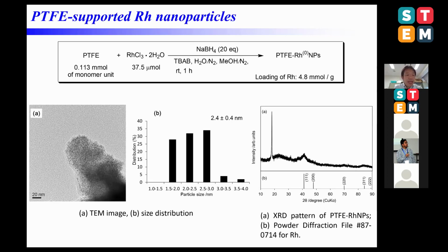PTFE-stabilized rhodium nanoparticles were also prepared using sodium borohydride as a reductant in the presence of TBAB. The formation of PTFE rhodium nanoparticles was confirmed by TEM and XRD spectra.